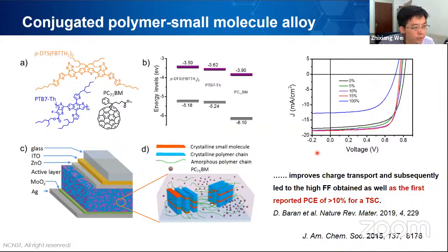We found a really good strategy we call the ternary strategy that can really increase the efficiency while keeping the material with good solubility in common solvents. We use small molecules to increase the crystallinity of the polymers, and then you can get a really good alloy of the small molecules with polymers, showing this works after combination with different kinds of materials. Actually, we showed the first PCE higher than 10 in ternary solar cells.